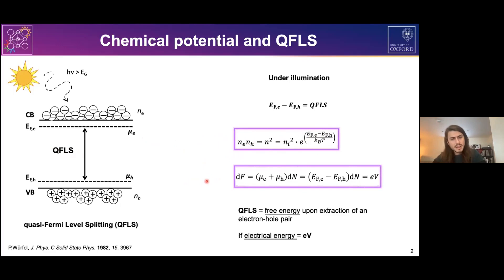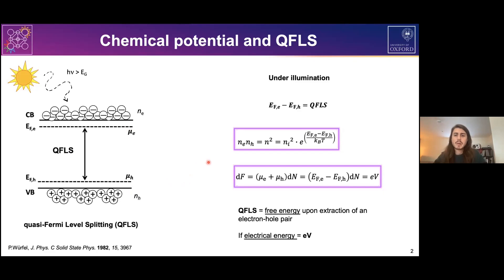Using two equations, I'll show why this quantity is so important. First, we can relate the quasi-Fermi level splitting to the free carrier density in our device — the magnitude of this splitting corresponds to the density of free electrons and holes, which we want to maximize in a solar cell. Second, we can express the quasi-Fermi levels in terms of chemical potential, so quasi-Fermi level splitting represents the free energy gained upon extraction of an electron-hole pair, which relates directly to the VOC of the solar cell.